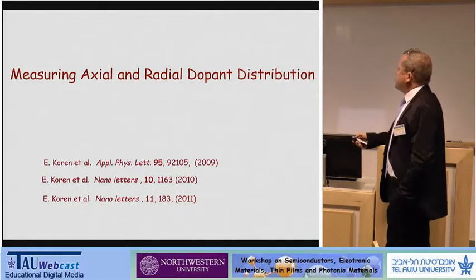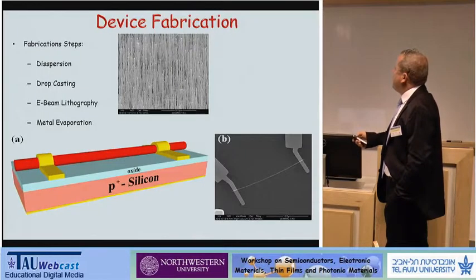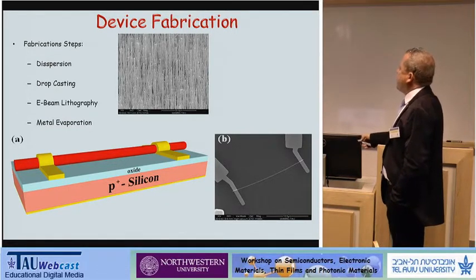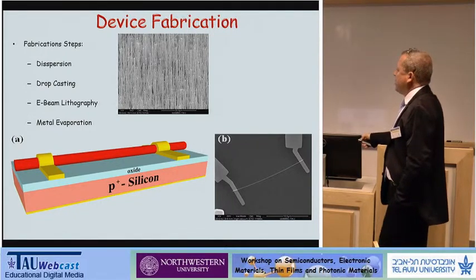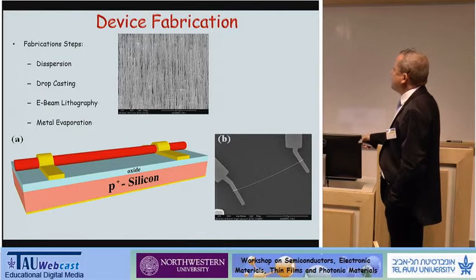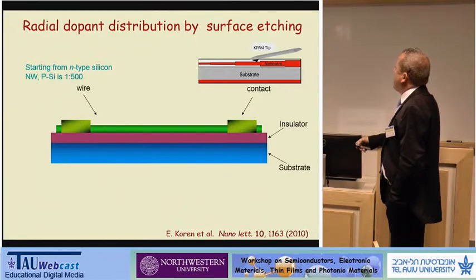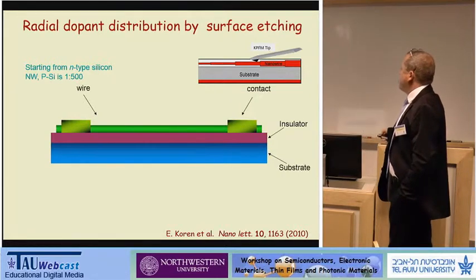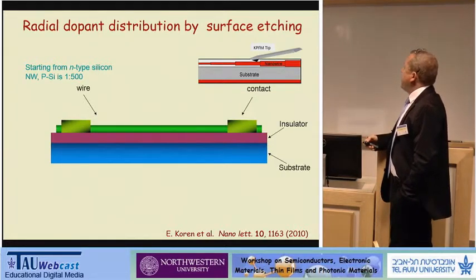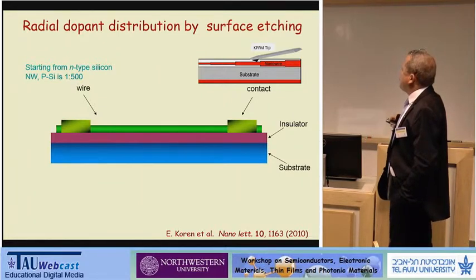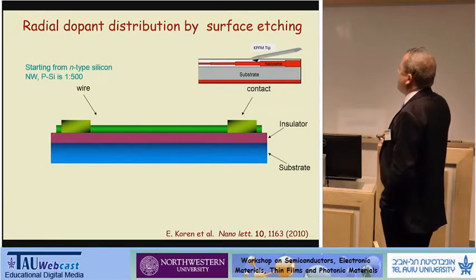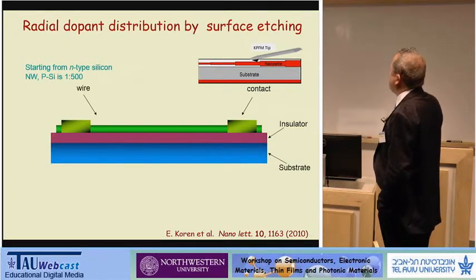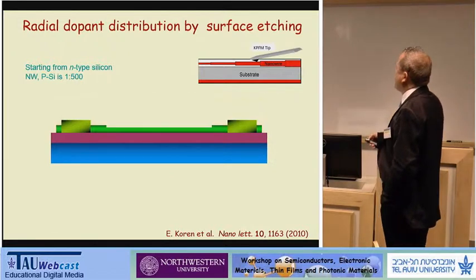So I'll just summarize what we have done since 2009. And the big issue that we worked with is how to measure the radial dopant distribution. So we fabricate a backgated silicon transistor, where this is the channel of the transistor. So we start with a forest like this. And this is the end device that we fabricate here. And a good method that Elad Koren, the PhD student that started this work, who is now at IBM Zurich, devised, a very clever method by which you etch successively the nanowire, form steps, as I will show you here.